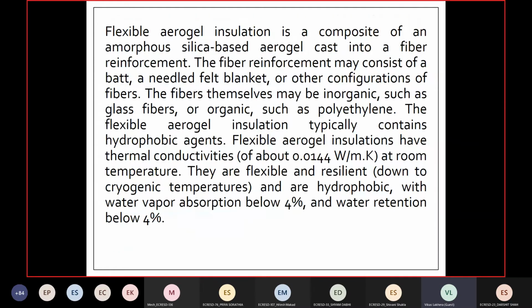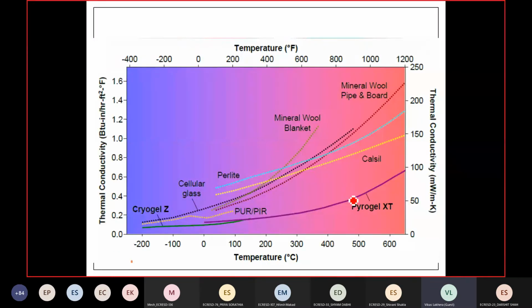Your pyrogel is here, as you can see, and this is the conventional mineral wool blanket that you are using. As compared to pyrogel, you can see how the characteristic of the insulation is. If you require this much thickness of mineral wool, you can work with this much thickness of pyrogel. So there is a lot of reduction in the outer diameter of the pipe. Especially in pipes it is very effective, because your outer surface area will be reduced, and from there only you are losing heat. So even though wall temperatures are the same, the outer cross-section area is going to be lower when you are using pyrogel as compared to mineral wool.